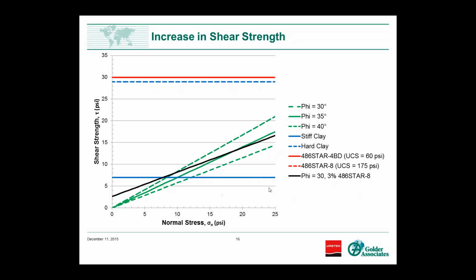So you can see that at shallow depths, it's definitely higher than even the 40 degree friction angle material. And then towards the deeper depths, it's still fairly close to the 35 degree friction angle. This is obviously a simplified model, but I wanted to illustrate that if you can feel comfortable that you've put that much material into the ground, then there is definitely going to be a shear strength increase. And this black line too, instead of the 8 PCF material, one of the more common ones they use is the 4 PCF product, which has slightly lower strength, that's the red line up at the top. If you can do 10% volume replacement, that's roughly equivalent to what that black line is showing.